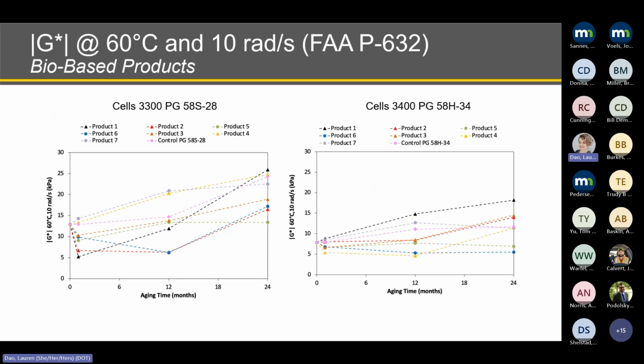The data presented on the previous slides is now summarized here in these two graphs. You can see on the left side, the treated surface or bio-based product, considering the control PG 58S-28. And on the right side, the same bio-based product, considering the PG 58H-34 binder. You can see that first, there is a significant difference in how these products are responding for the neat binder and the modified binder.